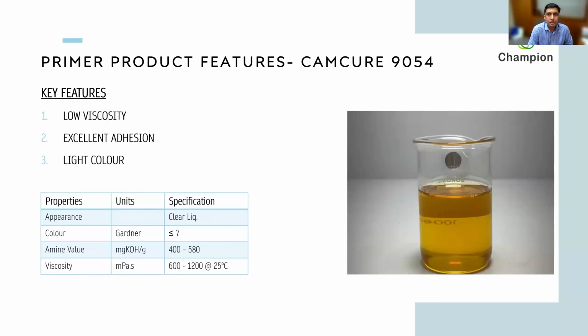Coming to the first curing agent, which is CamCure 9054, which is very good for primers as well as intermediate coats. This is a low viscosity product. It gives excellent adhesion, and that's the reason this is typically recommended when it comes to primers. In terms of chemistry, this is the Polyamidoamine chemistry, and it continues to be a very low viscosity product, unlike many other polyamides or amidoamine products.